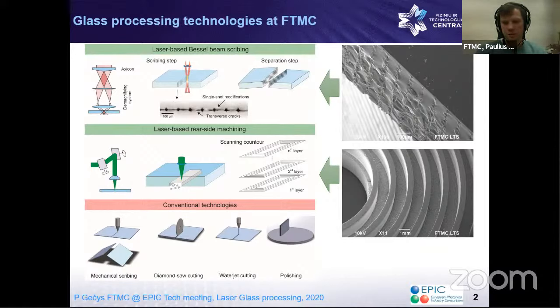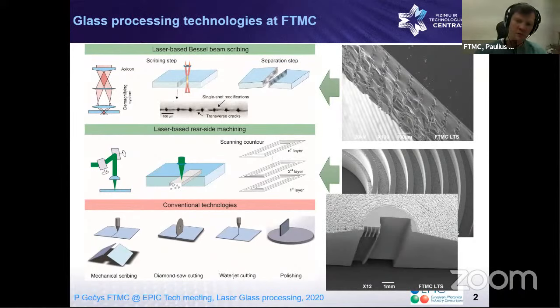And it's a taperless process. We heard today that we discussed low taper angle processing. Also, this technique is taperless. You have no taper, so it's completely vertical. Another advantage is that you can apply such a technique for hole drilling, for through cutting, and for 2.5D milling as well. And if you combine it with other laser-based techniques, for example, laser modification and chemical etching, you can make really interesting components.